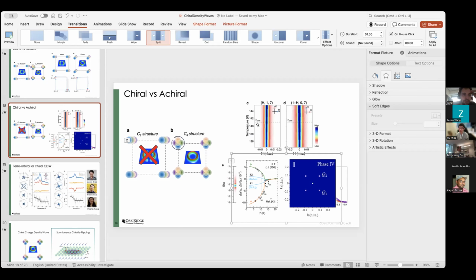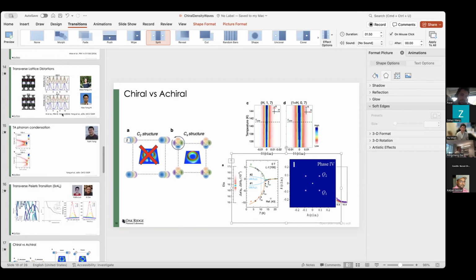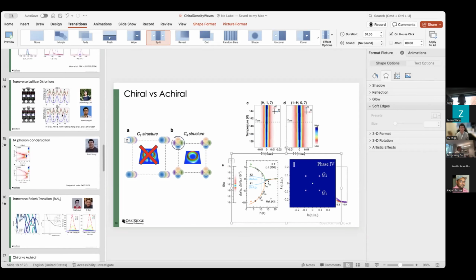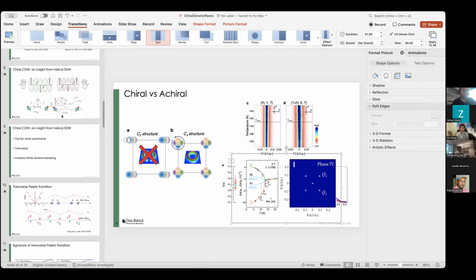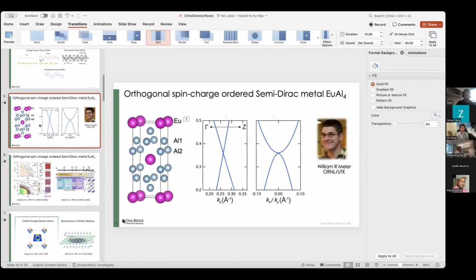Is it a highly two-dimensional material or not? No, you can cleave it, but I don't think it's 2D. It has the same crystal structure as the iron-based superconductors, except you replace the iron with europium, right? Yes. Europium itself has a BCC structure. So if you cleave, I think you're going to expose the europium layer around here.